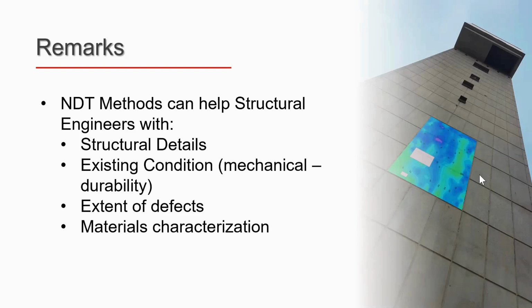Then you can use a bunch of NDT methods such as ultrasonic pulse velocity and the pulse echo technique to verify structural integrity of concrete. These are important when it comes to mechanical durability of concrete and other problems such as detecting voids and cracks in the concrete. If you also want to find the extent of defects, these NDT methods are extremely beneficial. So you can limit your repair and remedy work to areas that are really in poor condition.